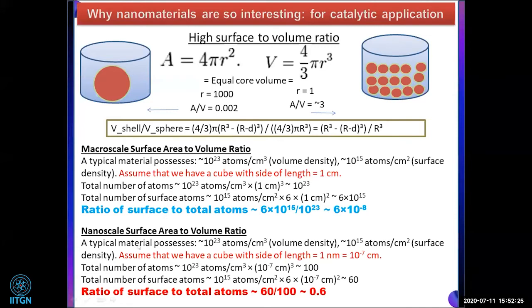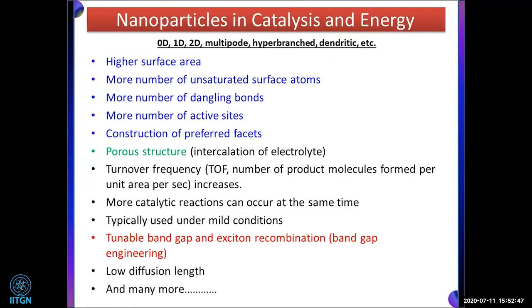Now see, surprisingly, it is a very simple calculation, and you can see the ratio of surface to total atoms in case of the 1 nanometer particle is 0.6. That means a 1 nanometer particle has almost 10 to the power 8 times more surface atoms. So when we have more atoms at the surface, we'll have more unsaturated surface atoms,